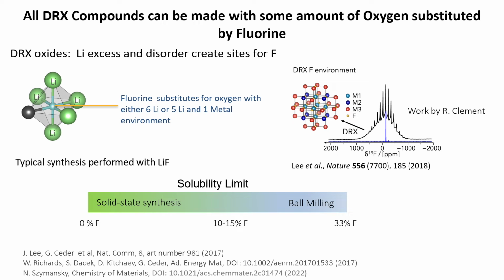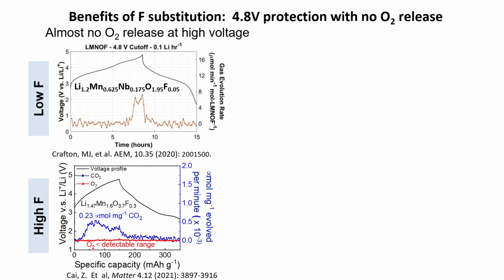Okay. Another benefit that we had not anticipated, but found later, is that these materials can take up fluorine in the synthesis. The reason they can do it is because statistically they have some environments where there's a lot of lithium around the anion, and fluorine particularly likes that, and so fluorine substitutes in there. Again, something much harder to do in these layered ordered oxides. And we've worked with Raphael to confirm this with NMR, because of course it's quite hard to detect fluorine in your materials by other techniques. Fluorine does great things for you.